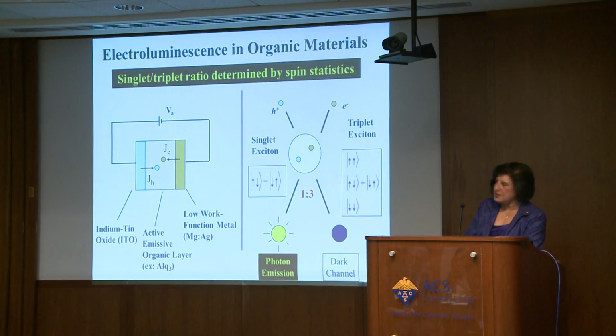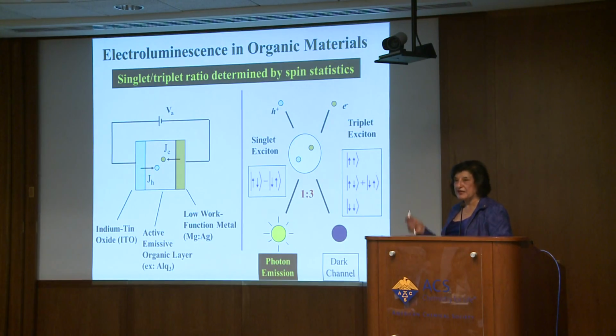two electrodes. Just to show you, for those of you who are not familiar with the function of an organic light emitting diode, I simplified the picture here. You have a very thin layer of the organic emissive layer, much thinner than your hair, sandwiched between two electrodes, a transparent electrode, which is typically indium tin oxide, and a low work function electrode. So when you apply a voltage at the cathode, electrons or negative charge are injected, and holes or positive charge are injected, and when they recombine, you form an exciton.